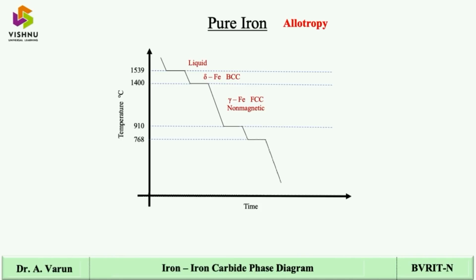Below 910 degrees centigrade it will again transform into another crystal structure which we call alpha iron, which is again a body centered cubic crystal structure, and it's also non-magnetic. And below 768 degrees centigrade the crystal structure will be the same BCC alpha iron, but the non-magnetic form will change into a magnetic form, and this temperature is also called the Curie temperature.